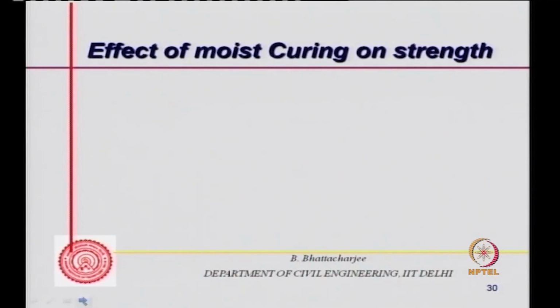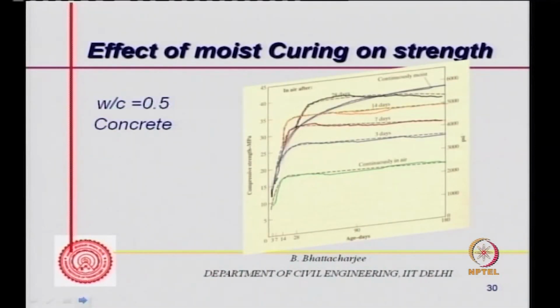Now, how do we do curing? We do moist curing. Supposing I have a water cement ratio of 0.5 concrete, and if I cure it continuously submerged, the strength will increase in this manner. Give it 28 days cured, strength will increase in this manner. 14 days cured, strength will go like this up to 14 days, and then it will flatten out. Continuously moist cured will go like this.